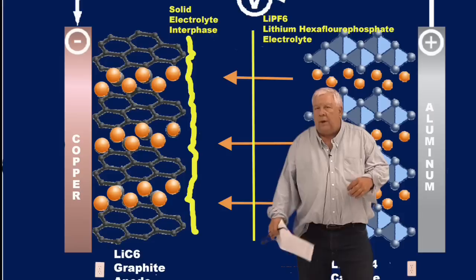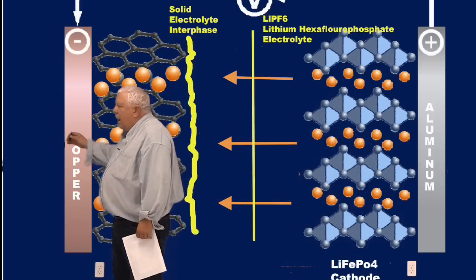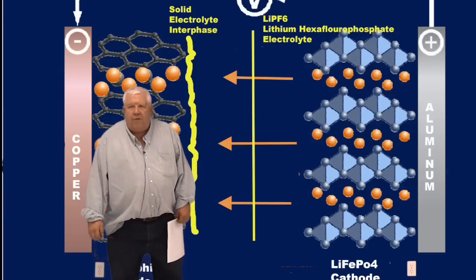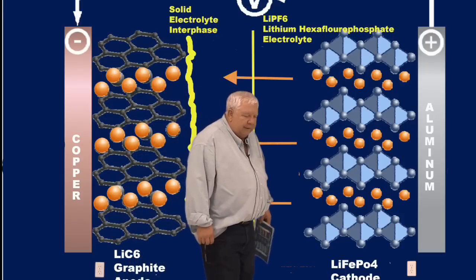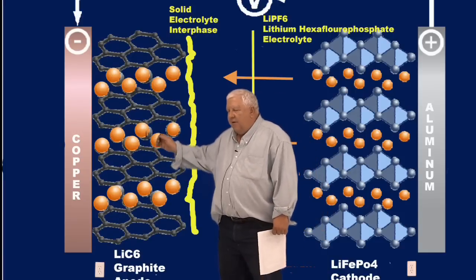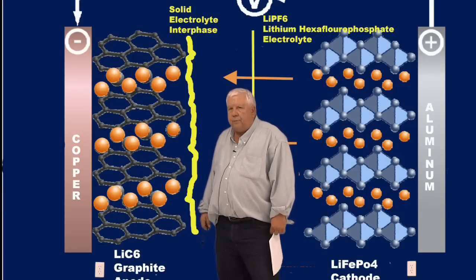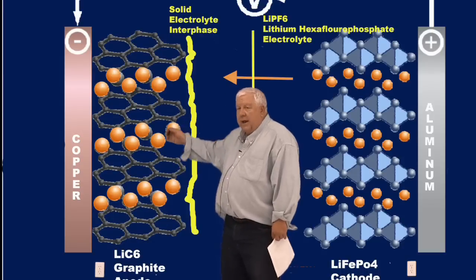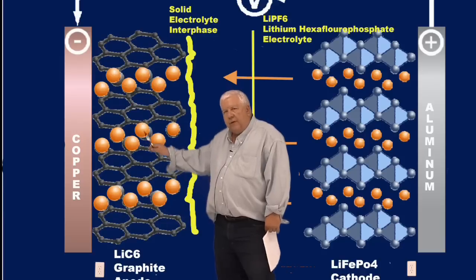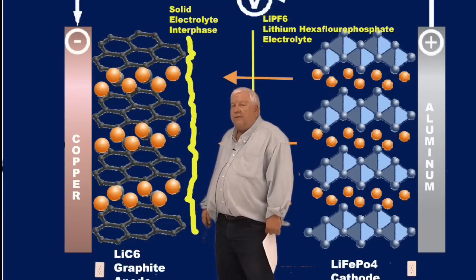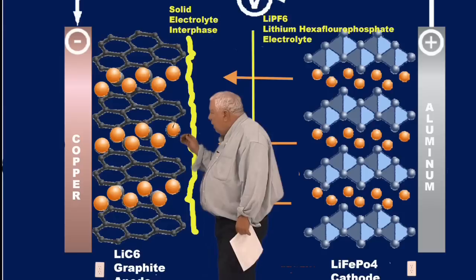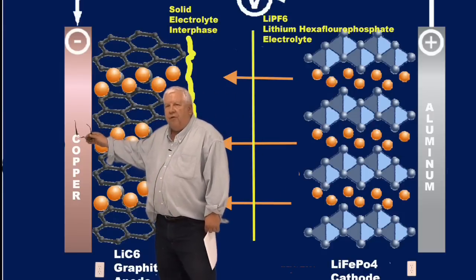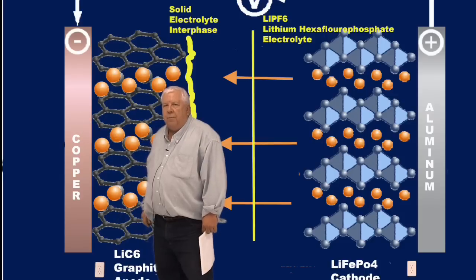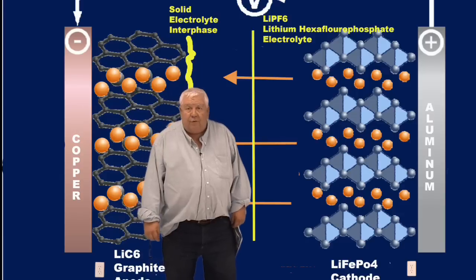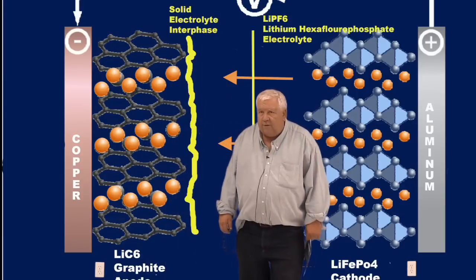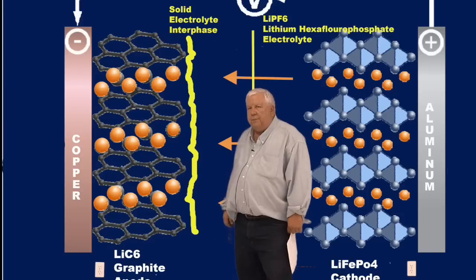This starts to occur below 1 volt. The copper begins to oxidize and so essentially dissolve and give off copper ions into our battery cell. And that copper plating, every place that appears, reduces our ability, copper plating on that SEI layer. It builds up kind of on the inside of the SEI layer. Now the next time we go to charge the cell, our lithium can't get through there because of the copper. And so it builds up as lithium metal on the outside. And as it gets up to a certain amount of it, that starts to react with our solvents, and we have the same thermal runaway situation.